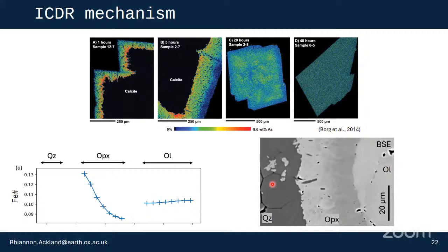An interesting feature of some ICDR mechanism experiments is the formation of zoning within the product phase rim. In these experiments, Borg et al. have put crystals of calcite within a fluid that contains both phosphate and arsenic. As the reaction proceeds, the calcite develops a rim of apatite. Initially, this apatite is phosphate rich and contains low proportions of arsenic. But as the reaction rim moves into the calcite, the proportion of arsenic in the apatite increases. This is thought to be because the porosity that's generated within the rim is only microporosity.